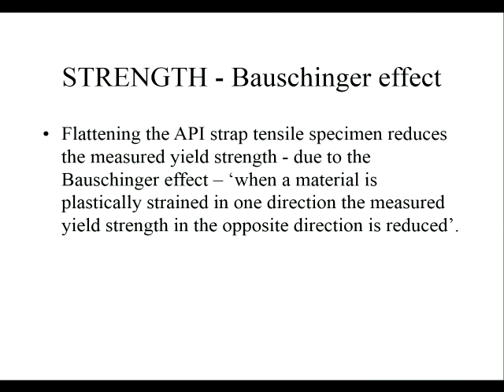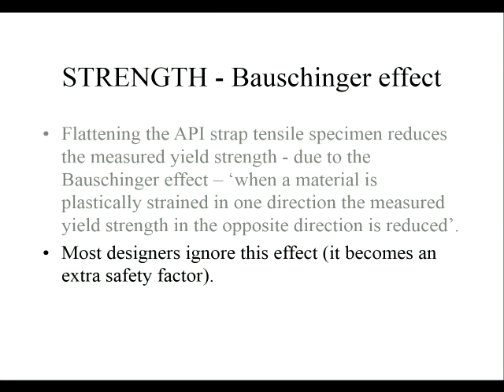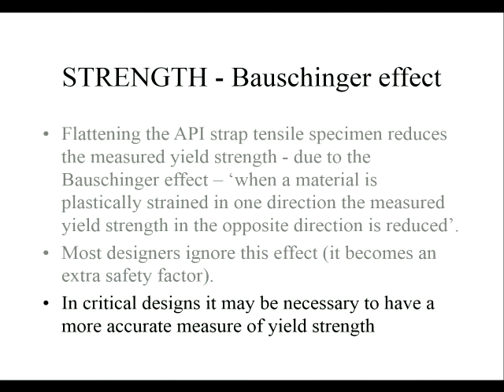So when a material is plastically strained in one direction, the measured yield strength in the opposite direction is reduced. And that's good because you're measuring the minimised yield stress, and if that still meets the specification, then the original one would have done. So we often just assume that this is an extra safety factor. But if your design is on the edge, and you don't want to be worried about whether this Bauschinger effect varies from sample to sample, and you want to really make sure that it works, then you might want to do a more complicated mechanical test. So in critical designs, you might have a more accurate measurement. But getting a more accurate measurement is expensive, so people don't tend to do it.